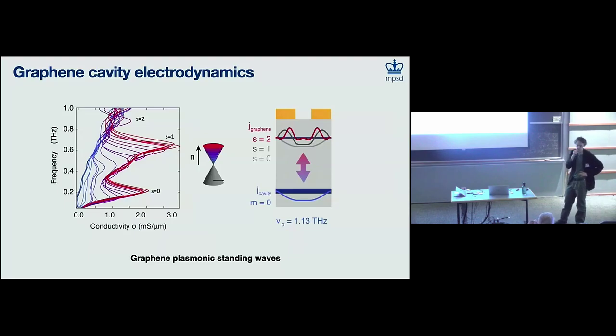So you want to generate and detect the terahertz? Yeah, generating terahertz at the single pulse level would just be a classical thing, where we reduce the power on the terahertz generator, and then do a statistics counting measurement, and once in a while you get a single terahertz photon. But actually, we did an estimate because I'm funded to do these kinds of things now. Just with our Auston switches, we estimate that we can already generate and detect on the order of 100 terahertz photons, just with our semiconductor switches. So getting 2 orders of magnitude by using these cavity enhancements and superconductors maybe isn't so crazy. But the generation, I don't know. Maybe you destroy a superconductor and you get, I don't know. But that sounds a little bit harder to get.